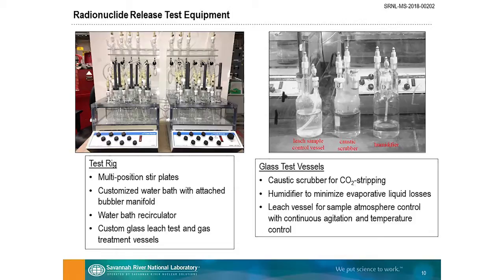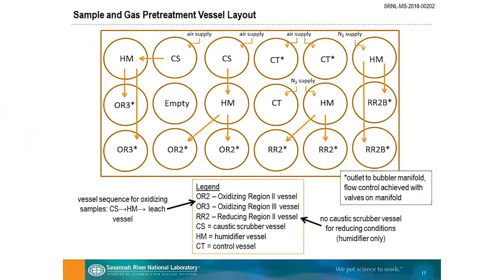That's an example of a caustic scrubber where we're just bubbling our air through 5 molar sodium hydroxide to strip out the CO2. And this is a humidifier vessel that either isolated the caustic scrubber from the actual sample or was used to, as I said, saturate the gas flow such to minimize evaporation from the actual sample. Okay, won't go through this, but the actual samples are the OR3, OR2, RR2 samples, and all these other vessels are to produce that atmosphere within the test vessel that we want. For oxidizing samples, it would go through a caustic scrubber, then a humidifier, and then through the leach vessel.